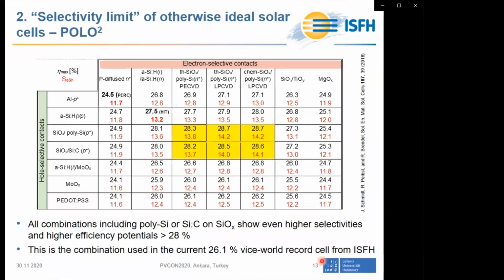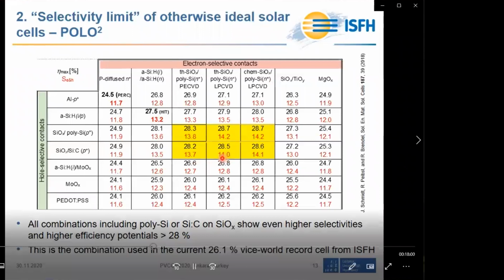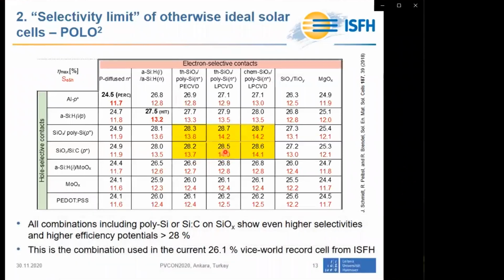Okay, let's move on to another very promising combination of electron selective contacts and hole selective contacts. In this case, consisting of a stack of a thin interfacial oxide covered with either P-type doped polysilicon for the case of hole collecting contacts, or N-type doped polysilicon for the case of electron selective contacts. These polysilicon layers may also contain other components such as carbon. For all of these combinations, we obtain very high combined selectivity values, exceeding 14, and the corresponding selectivity limit is also very promising. It exceeds values of 28%. This combination of contacts was actually implemented also in our 26.1% cell, which is still the record for homojunction silicon single junction cells.